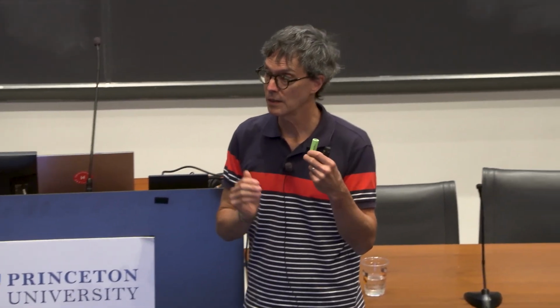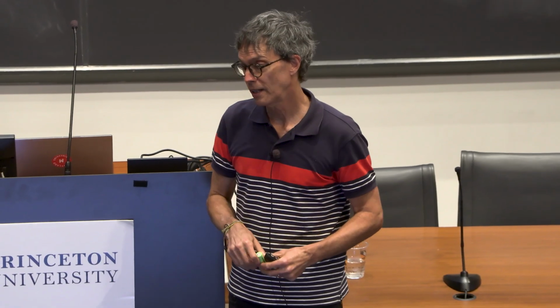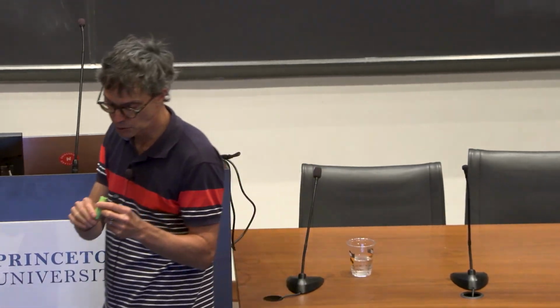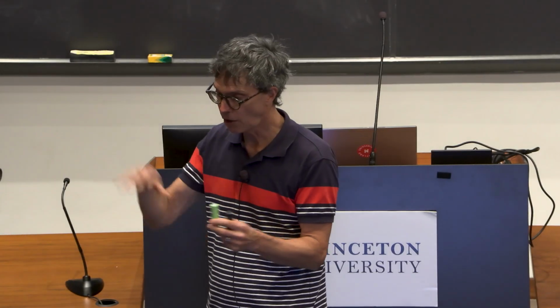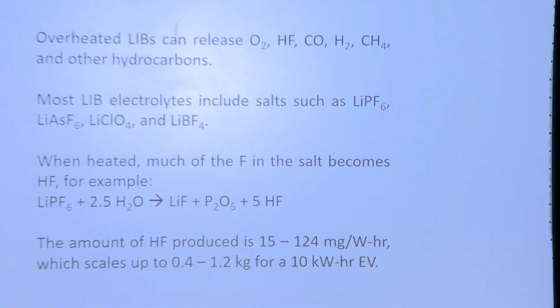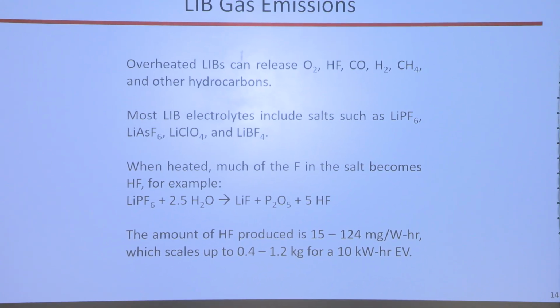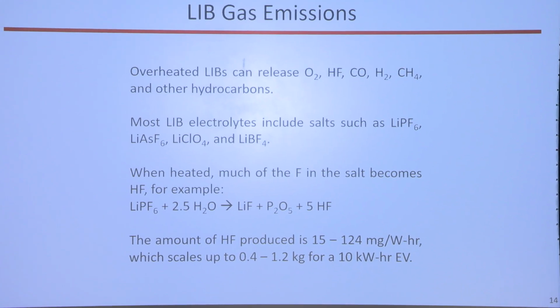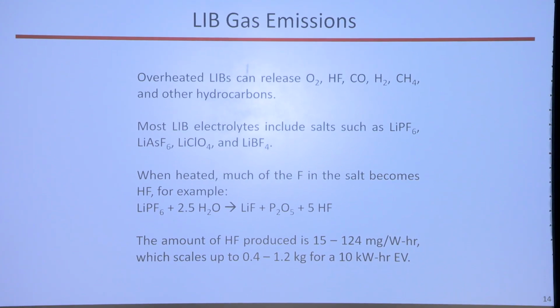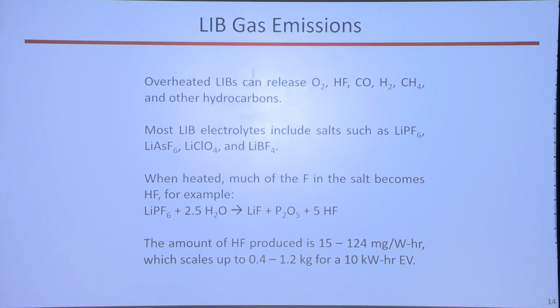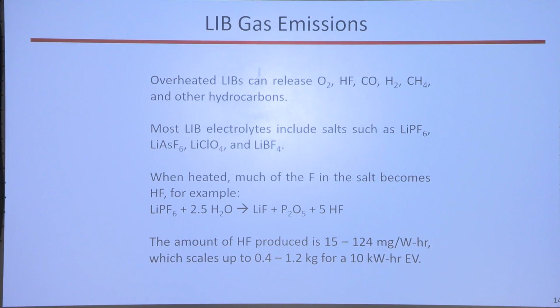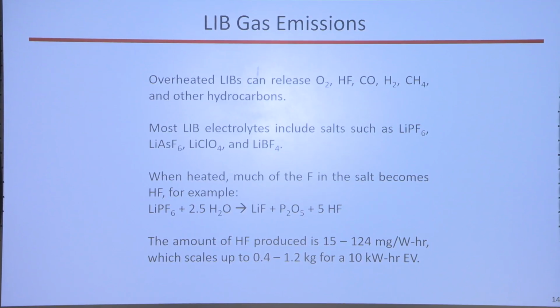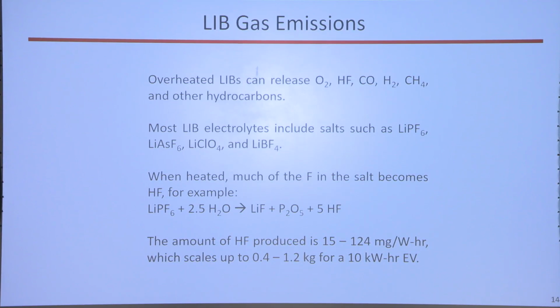When these batteries burn, usually they just vent all their contents. When the vent goes, usually it's hot enough and it's still burning, all the electrolyte goes out. And with that electrolyte, remember there's salts. You need lithium, and these salts need fire retardants that may have fluorines in them, and you release some real toxic gases. A lot of people, this is kind of a secret. They don't want to, it's a trade secret. They don't want to tell the world what they're putting in their batteries, so it's a little bit hard to know. But lots of researchers have tried to measure, and they find that these things release oxygen, that's fine.